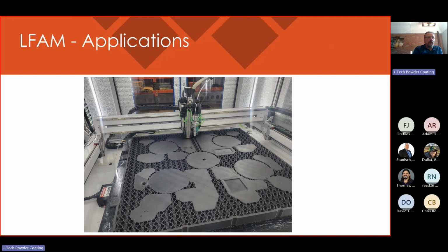Prototype. This is a prototype vacuum mold being done by one of our customers. This customer was purchasing 90 wooden prototype molds a year. And due to the heat of the process, they were only able to form about 10 parts on the wood mold before the mold was ruined. It would delaminate. So we did some work with them on using ABS carbon fiber, and with this material, they can do 50 prototype parts before the mold is shot. So it's a big advantage for them.